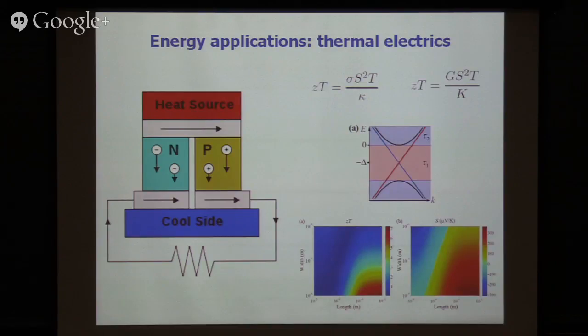Previously, we were very frustrated because it looks like there's some intrinsic relationship between them, and no matter how hard you work, it looks like we're stuck at ZT equals 1. But now we have another tuning parameter, which is simply the geometrical proportion. We also have a proposal for how to increase the Seebeck coefficient by tuning the Fermi level close to the bottom of the conduction band. The Seebeck coefficient measures the asymmetry between the states above the Fermi level and the states below Fermi.